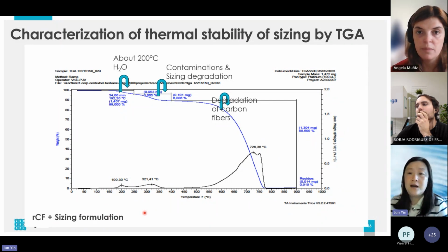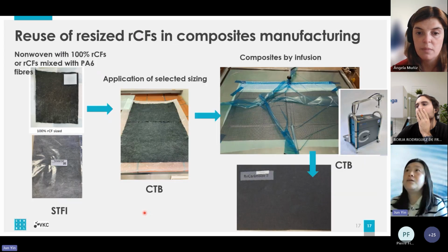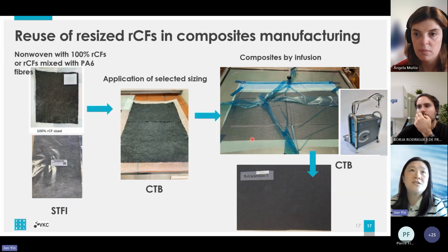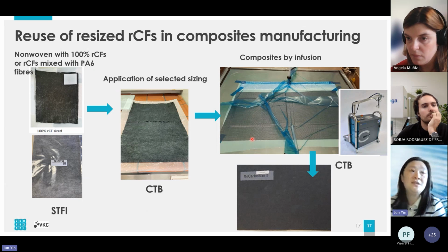So in our composite manufacturing, we used infusion, vacuum infusion. The temperature is about 40 or 50 degrees. So the sizing can be stable at this temperature.